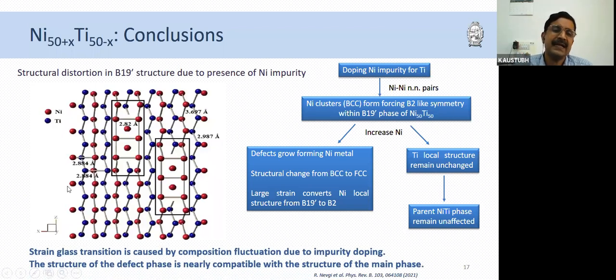So we said that strain glass transition is caused by composition fluctuation due to impurity doping. And the structure of the defect phase is nearly compatible with the structure of the main phase. And that is also seen here. You have almost about 2% difference in the nickel-nickel bond length in the B19 prime phase, which is 2.884, whereas in the body-centered cubic phase, it is about 2.82 or 2.84.